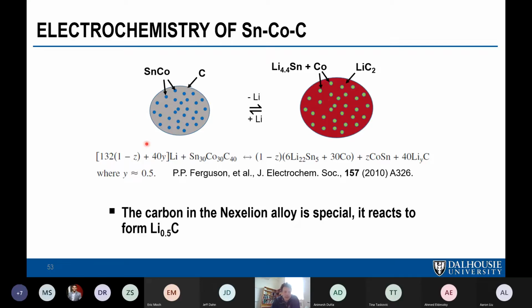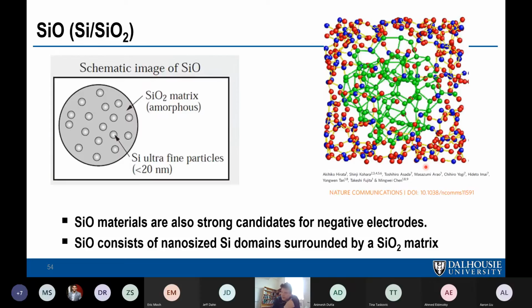So anyways, you lithiate this material, and as with many alloys, it can phase separate during lithiation. And in this case, the tin cobalt phase separates so that you make lithium tin and cobalt metal. And then again, the carbon matrix can make LiC2. Another material that's presently commercialized is SiO.